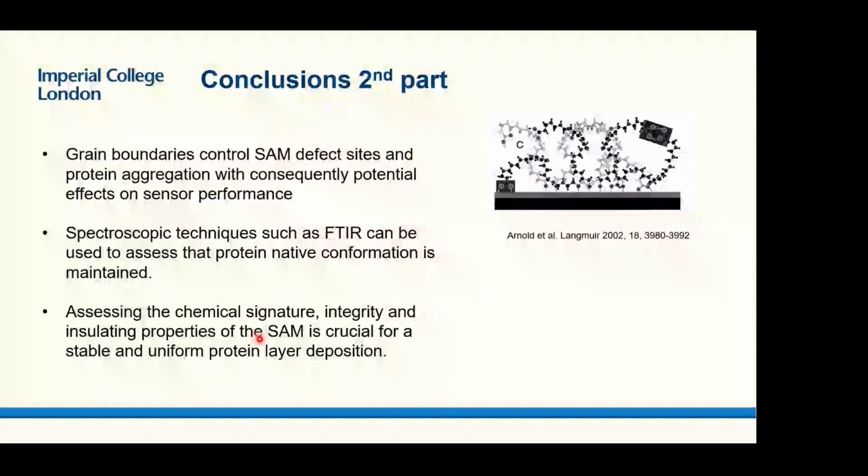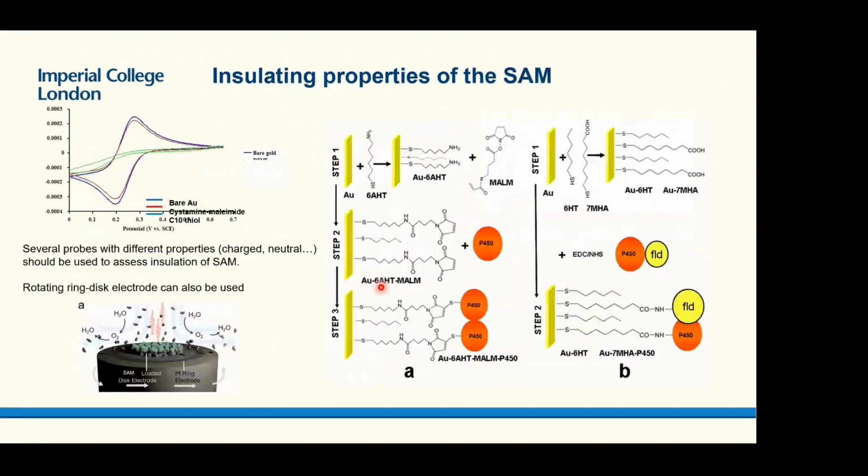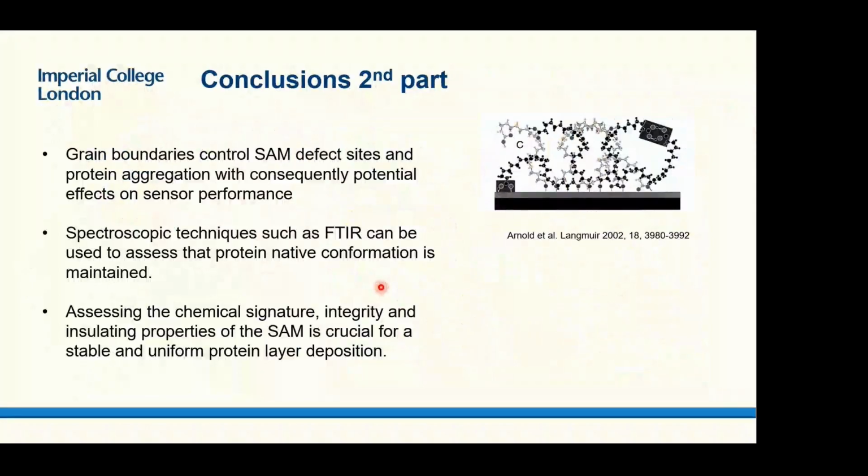And just to say that in terms of the self-assembled layer, you have to remember that they do not, as drawn, lie nicely like a carpet, all very nicely packed. You have to be careful when you start forming the self-assembled layer, because if you don't control the chemistry, the chemical reaction, you can lead to the formation of this disrupted structure.